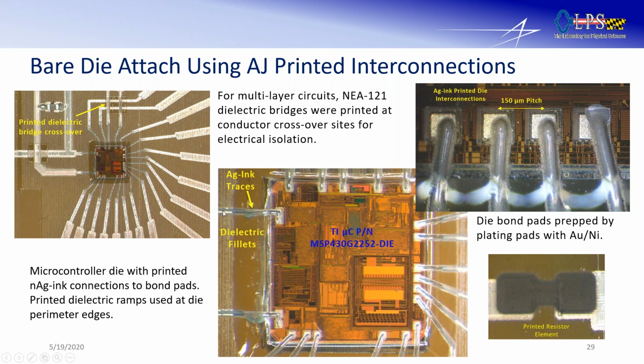So you can kind of see it here. It's going from the printed wiring board up the dielectric ramp and then to the bond pads on the chip. These were normally wire bond pads. And so we're printing like 50 micron lines to bond pads that are like 150 microns in pitch. So it's really clean. We're really pleased with how this printed.